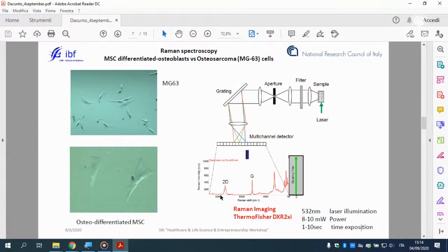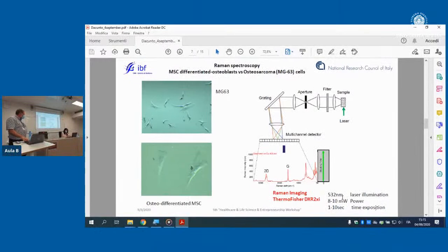Okay, we applied Raman spectroscopy and SERS spectroscopy to different populations of cells, from differentiated mesenchymal stem cells to the cancer cell line MG63. This is an experimental sketch of our system. It's a Raman spectrometer supplied by Thermo Fisher, and it is particularly improved by this collection part of the device, so having a very stable system. These are the parameters used for the experiment. We used green light, power from 8 to 10 milliwatt, and with exposure time from 1 to 10 seconds depending on the experiment.